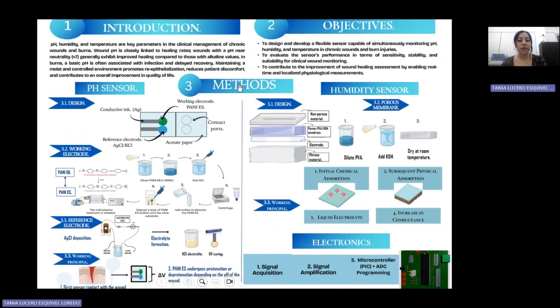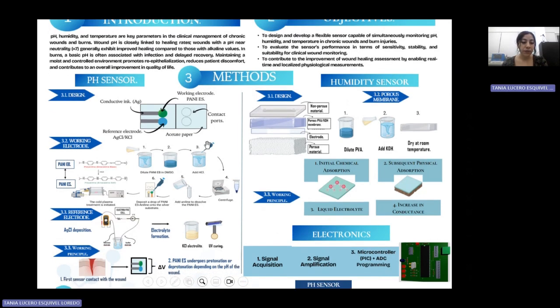Let me now describe in more detail how the sensors were fabricated, as illustrated in the figures of the poster. For the pH sensor, the sensor layer was based on polyaniline, a conductive polymer that changes its electrical properties depending on the hydrogen ion concentration of the surrounding medium. So, this polymer is sensitive to pH, but only in its conductive form. That's why it's important to do a functionalization to go from the emeraldine base, which is not conductive, to the emeraldine salt, which is conductive.